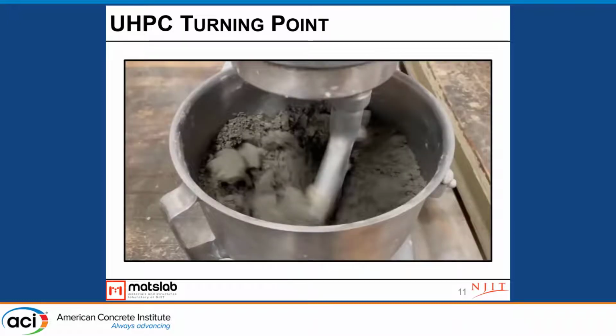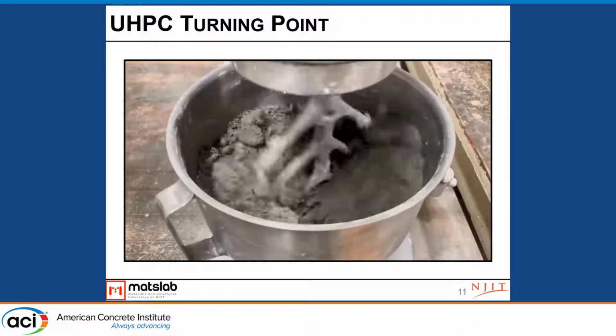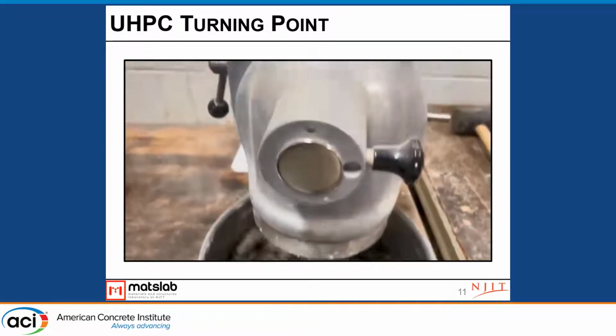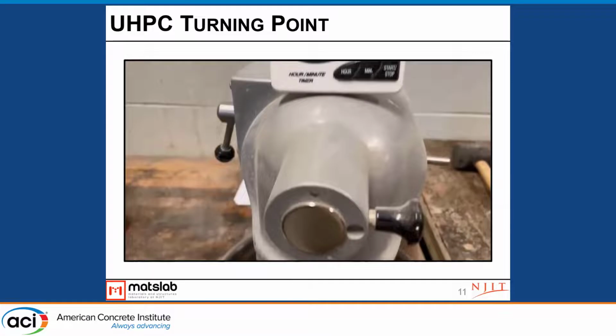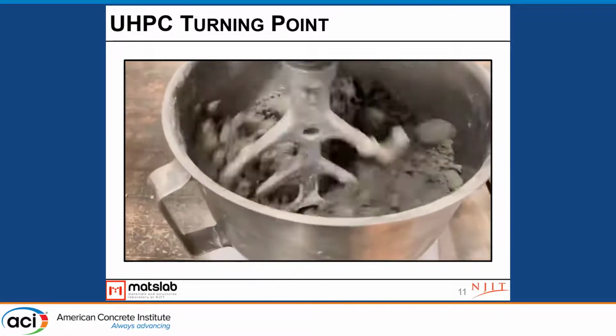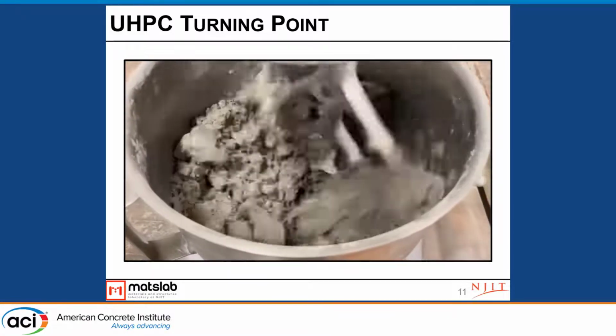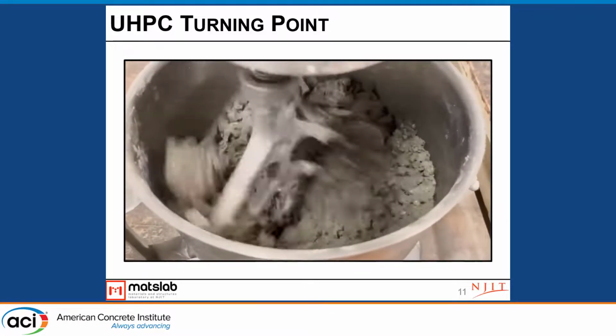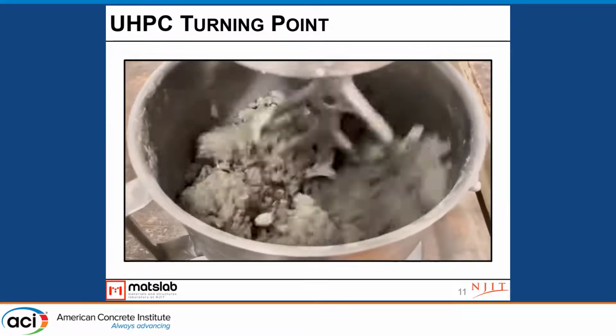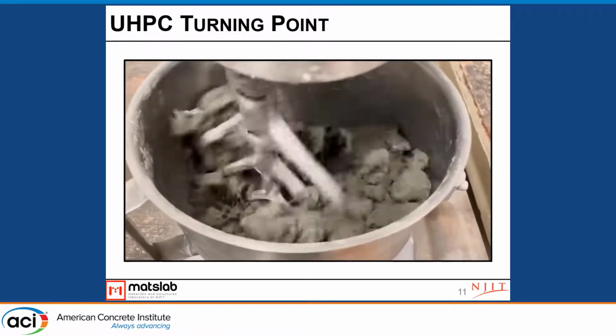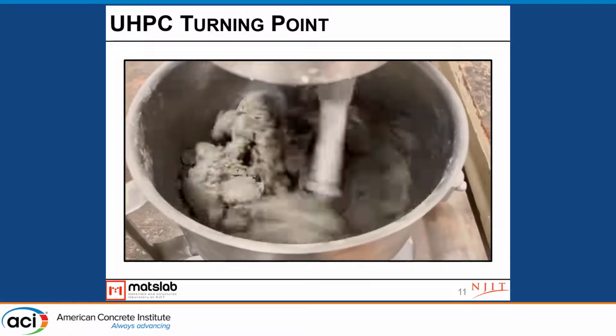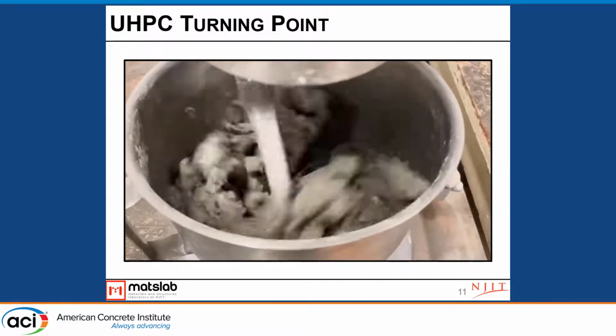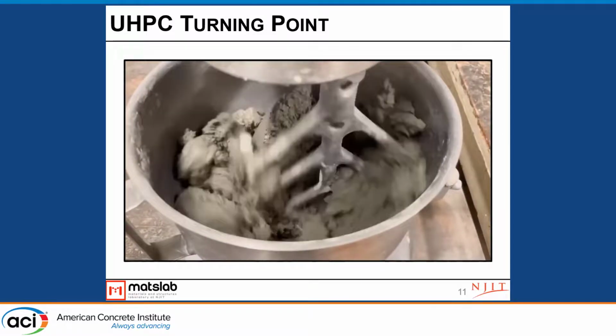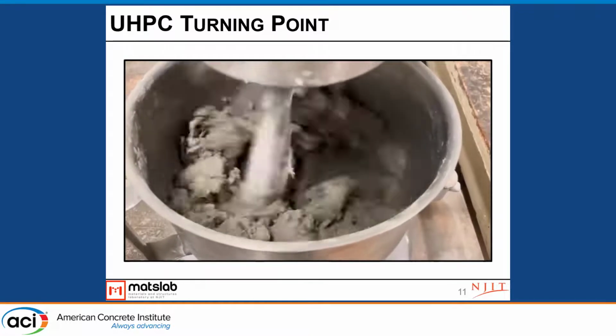This next one I did in a small Hobart mixer just to show the different stages of the mix. You see some clumps of UHPC, and for this mix it's 12.5 minutes. This happens pretty fast. It's mixing for 12 minutes, and sometime between 12 and 13, it depends on the volume of the mix and the type of mixer you're using, these things happen, and 1 minute later you have something completely different from the powder you had in the mixer.